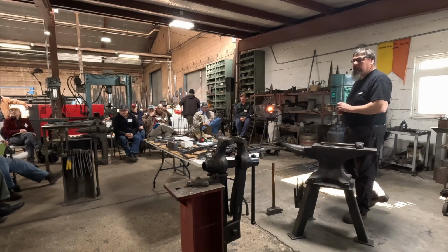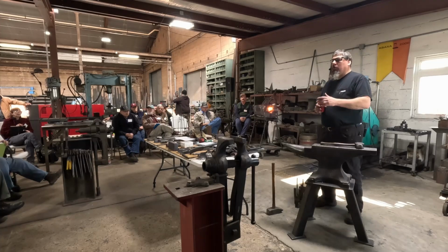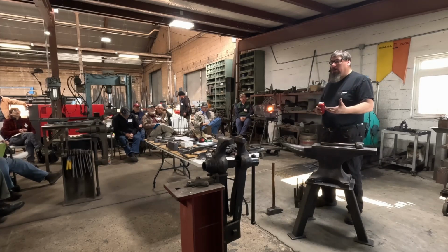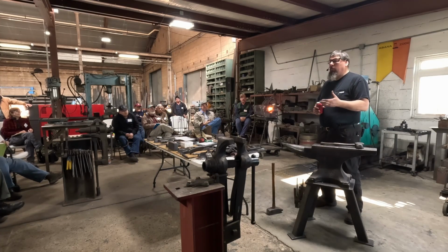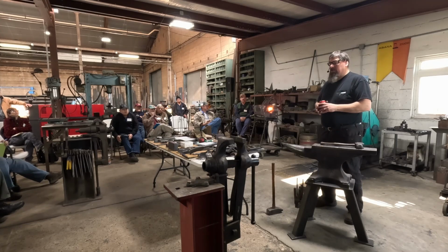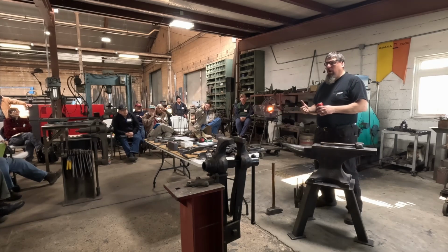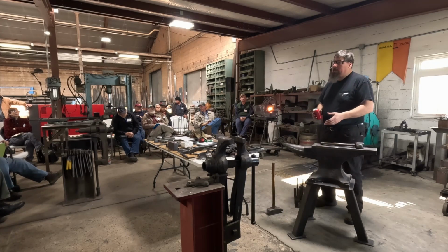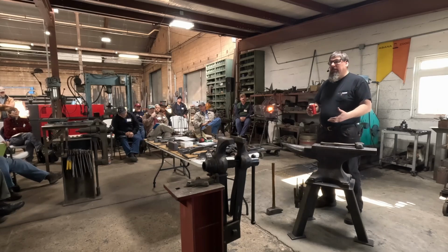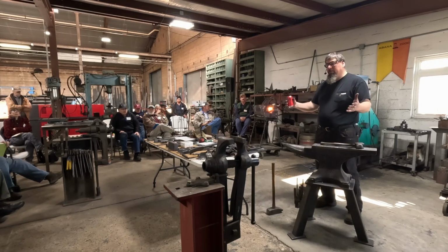I saw another question on this side. How often do you change your quench fluid? So the question is, how often do you change the quench fluid? Water has to be changed or cooled if it's getting too hot. We have some great big chillers that we can pump the water through, but there are times when that's not sufficient and you'll actually empty the tank out and bring fresh water in. Usually that happens more frequently in the summer when the chillers are not as effective. The frequency really just depends on how much metal you're trying to quench in a day or in a period of time.